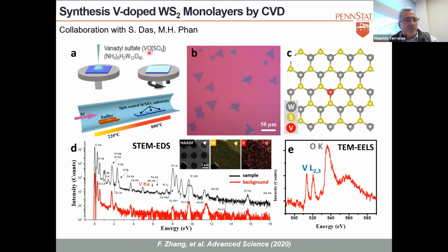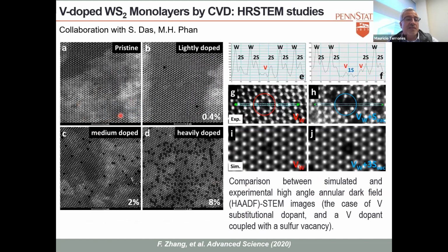So we used the vanadium precursor. This is vanadyl sulfate here. And then we used our tungsten precursor, which is this one. So we spin coat it, and then we use sulfur powder, we vaporize it. And what we ended up having is a vanadium-doped system, where you have the tungsten sulfide lattice and then you have vanadium dopants here. And then we can see the vanadium by EDS. And I will show you the STEM images, the scanning transmission electron microscopy images. So this is a pristine material.